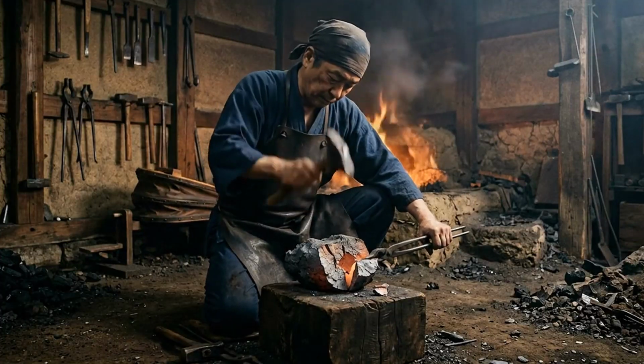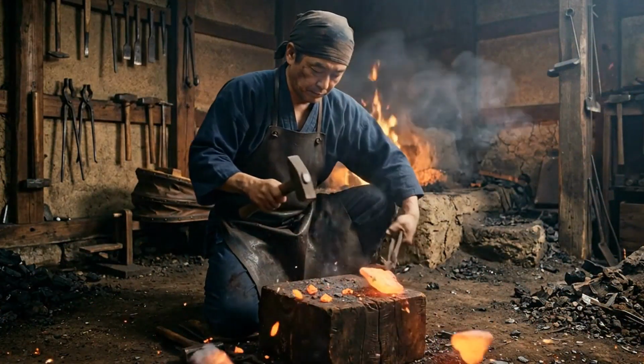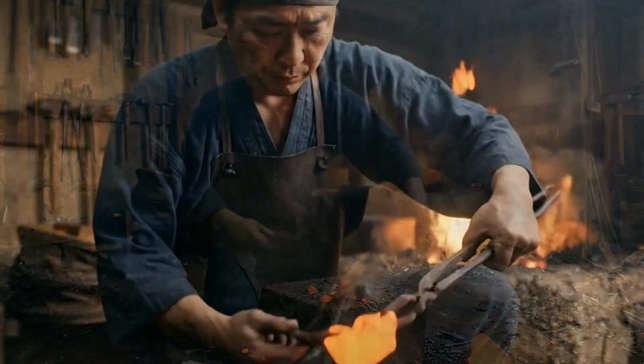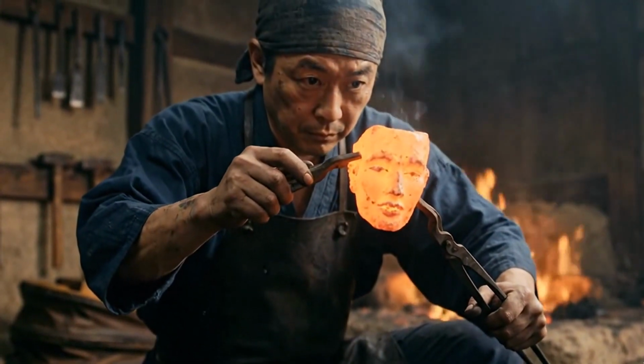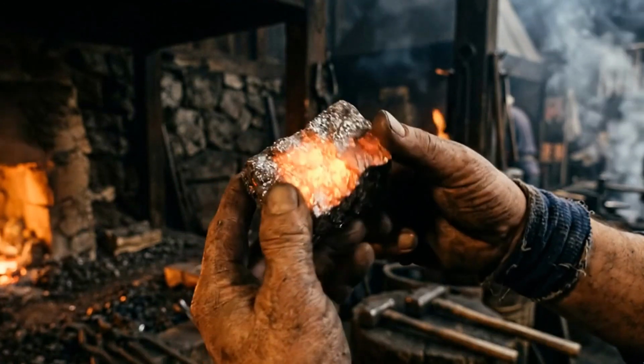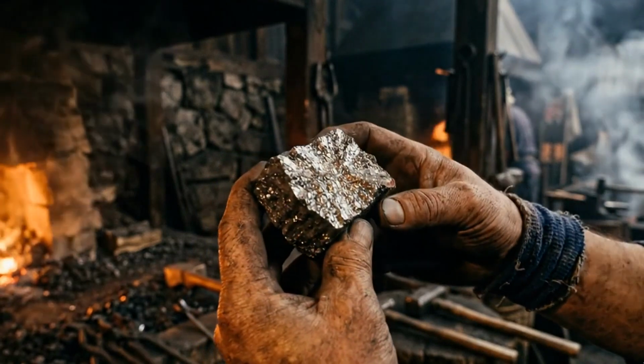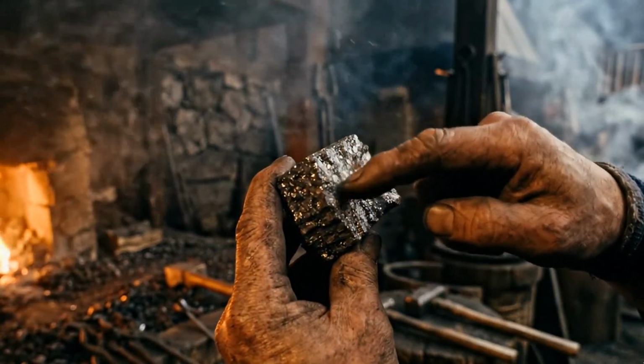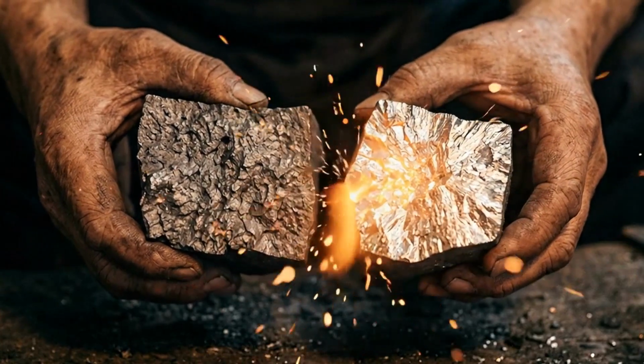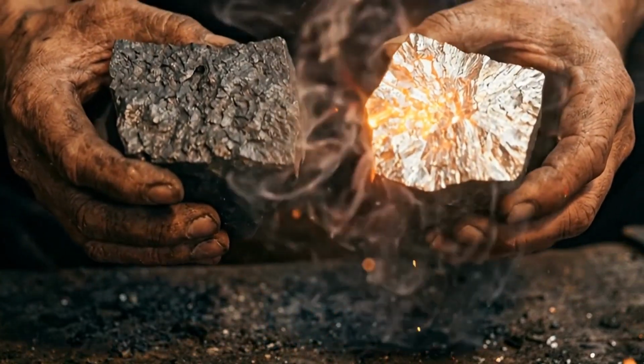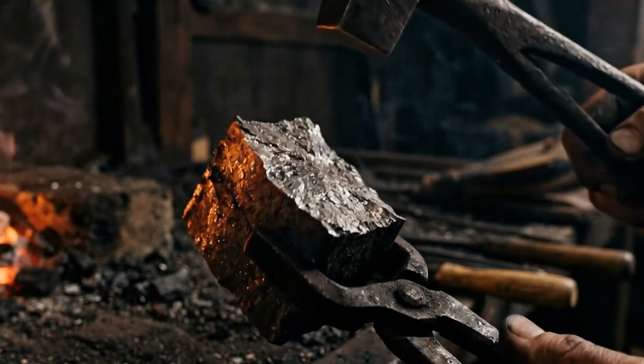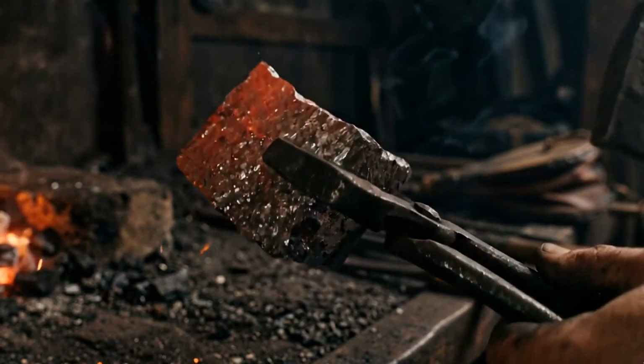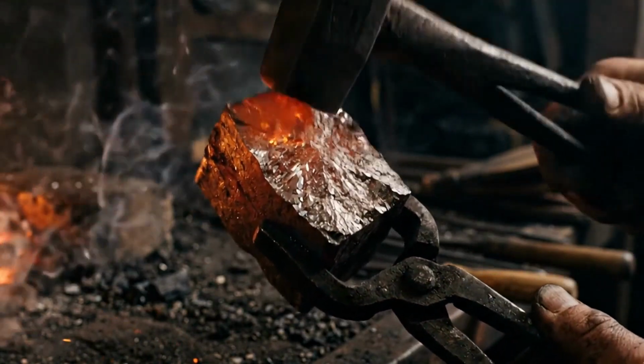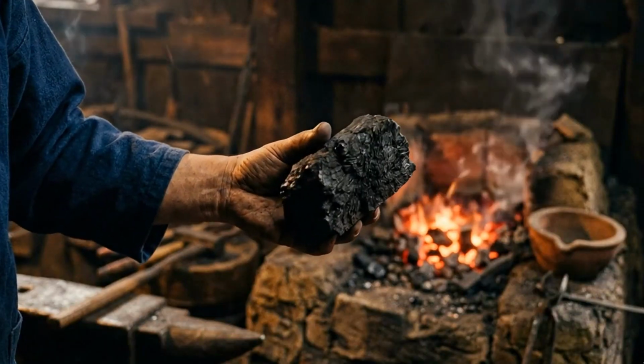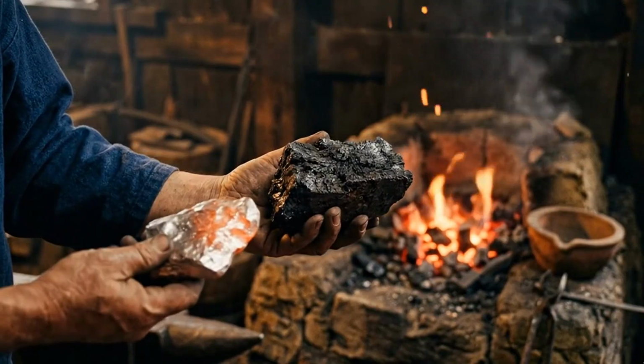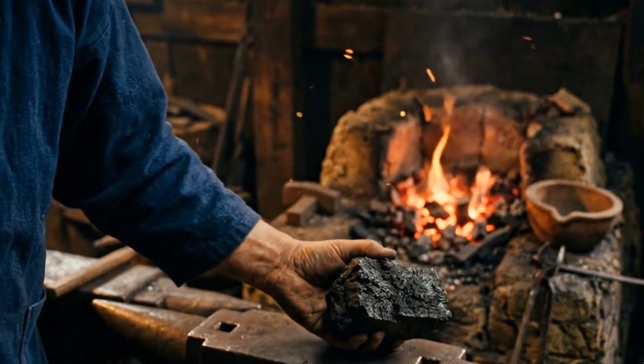When the tatara was broken open after the smelt was complete, the master swordsmith, the tosho, examined the bloom carefully, fracturing pieces away with a hammer to read the internal grain and carbon distribution. The color of the fracture face told him what he needed to know. A bright fine-grained fracture indicated high-carbon steel, hard and capable of holding a razor edge. A darker, coarser fracture indicated lower carbon iron, tough and resistant to shattering.